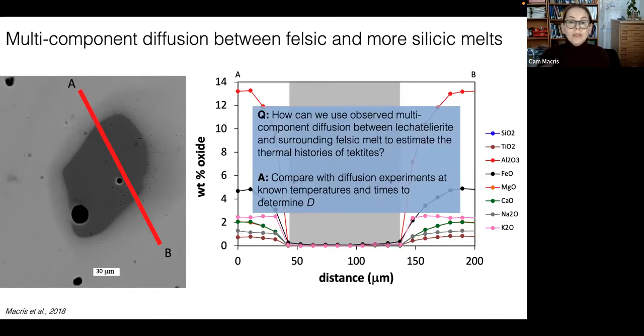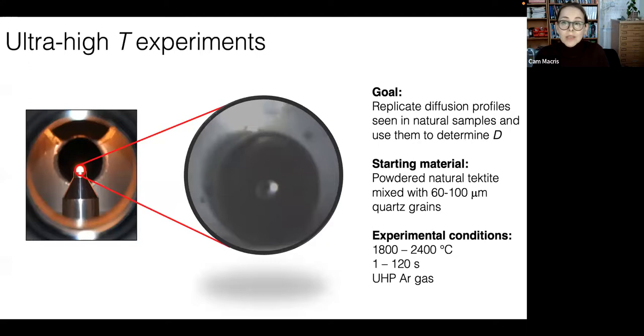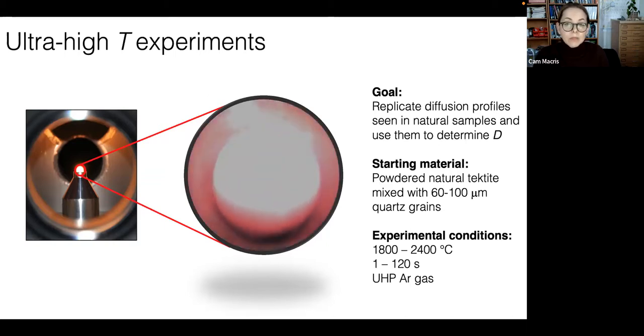How can we use this observed multi-component diffusion between the Le Chatelierite and the surrounding felsic melt to estimate the thermal histories of tektites? Well, the answer is that we would compare it with diffusion experiments at known temperatures and times so that we could determine those diffusivities or those diffusion coefficients. And so that's what we did. We did some experiments in the aerodynamic levitation laser furnace. We wanted to replicate the diffusion profiles seen in the natural samples and use them to determine the diffusivities.